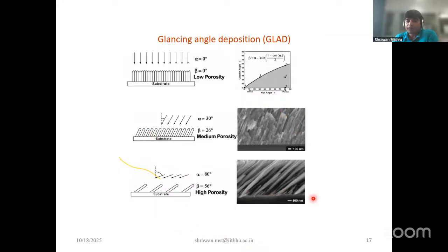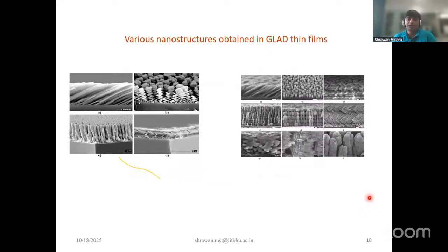In the growth process, when you are trying to grow magnetic material, there are various ways that you can grow different types of material, such as you can grow a nanowire on top of a substrate, or you can also grow a porous material where you have deliberately implanted some desired material in the pores compared to the other sections. So you are not only controlling the material, but you are also designing the material. So you have various ways that you can design these multiple structures. And here is the first demonstration that I am trying to show. The same material has been grown in different geometries, and you can see their microstructure. And not only that, later we found that their magnetic properties differ very significantly depending on the structure that we are using.